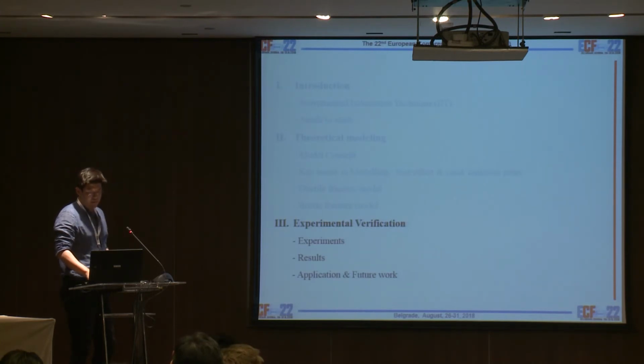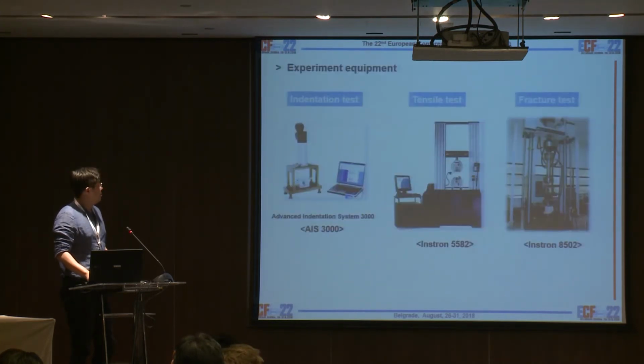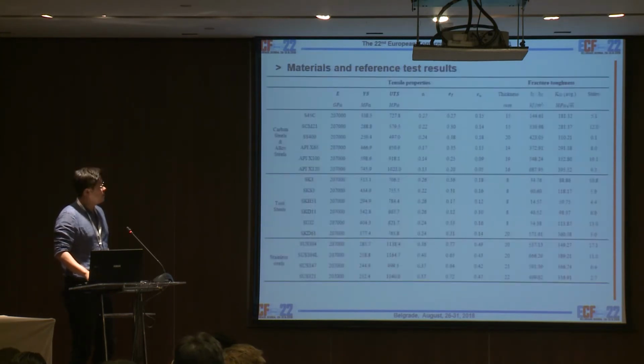So here is the experimental verification. We had the indentation test by AIS 3000 (Frontics), and the tensile and fracture tests were done by Instron. Here was the reference data. We got KJ values because the main purpose was to deal with surveillance specimens. We tested J-test and calculated KJC.